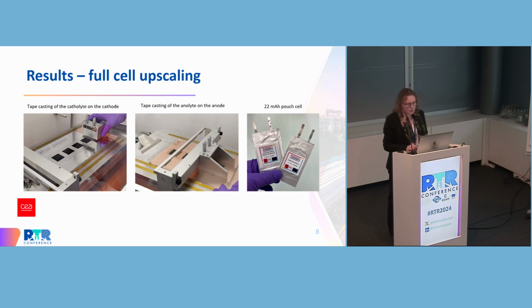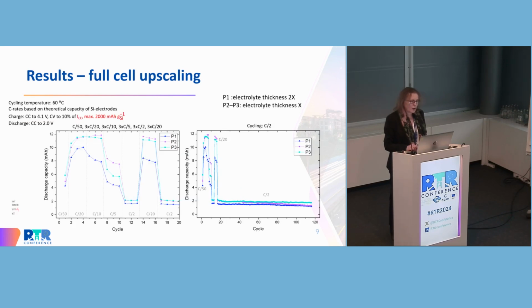As I said to you, the idea was effectively to use a classical method and process for manufacturing electrode. Here you can see some example of pouch cell that has been done with 22 milliamp-hours. Some example also of the cycling stability of this material is the following. Following the two electrolyte thicknesses, we have effectively some impact related to the electrolyte thickness and ionic conductivity that decrease slightly the discharge capacity. And after, when we are at higher C rate, effectively, it is the kinetic that is limiting the process, and we are able only to keep 10% of the capacity of the cell.